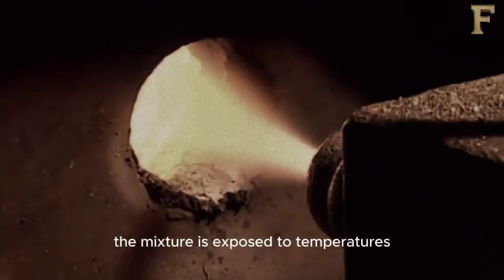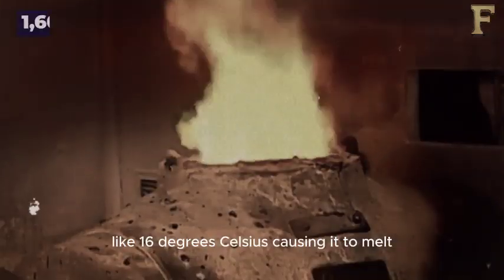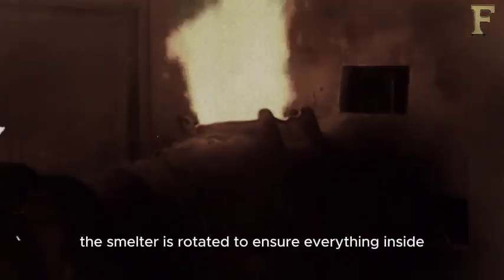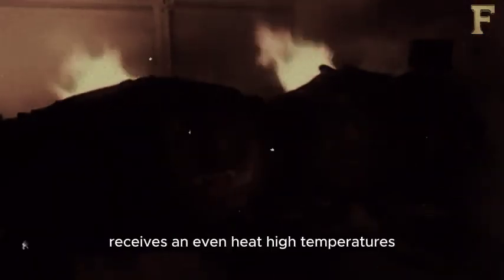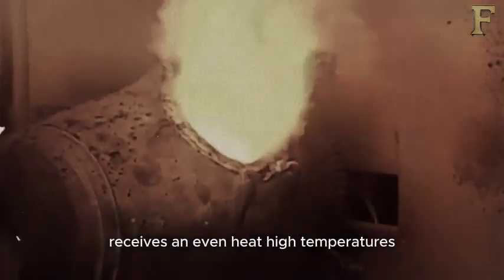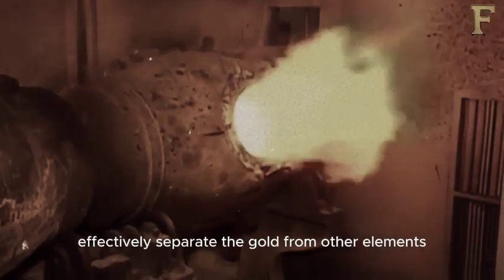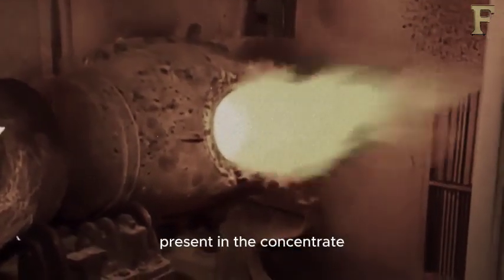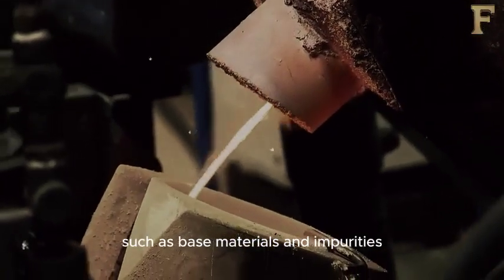Inside the furnace, the mixture is exposed to temperatures like 1600 degrees Celsius, causing it to melt. The smelter is rotated to ensure everything inside receives an even heat. The high temperatures effectively separate the gold from other elements present in the concentrate, such as base materials and impurities.